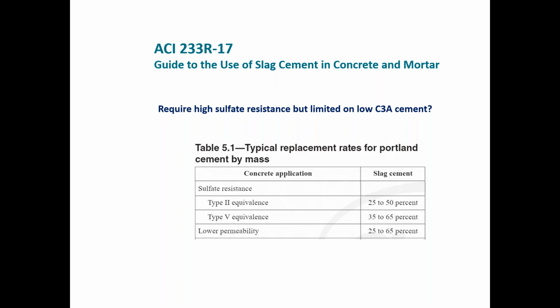And then for lower permeability, you can see that range just opens up from 25 to 65, and I would even say 15% is going to give you lower permeability. Any percent more than 0 when it comes to an OPC mix, you're going to get the benefit of lower permeability. But in these ranges, you're going to get the best effect of low permeability. So next slide.